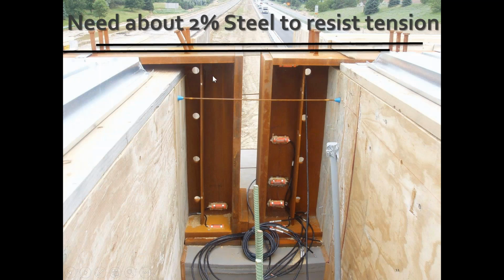This is another shot of the same bridge. Okay, you can see that steel block over here, end plate, and the steel girder. This is the concrete diaphragm. The sequence of the casting is that you fill this concrete diaphragm maybe halfway, and then you wait for a couple of days until that concrete is hardened. After the concrete is hardened, then you go ahead and cast the deck and the remaining of the concrete diaphragm.